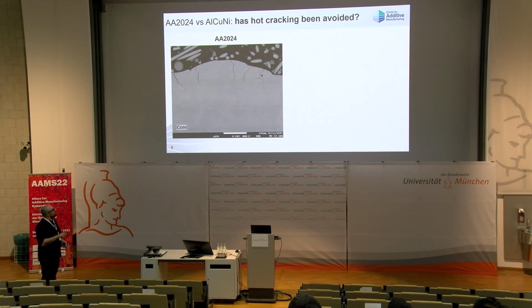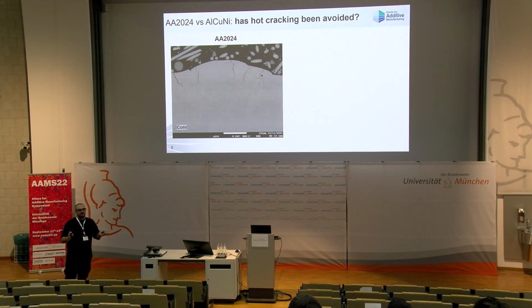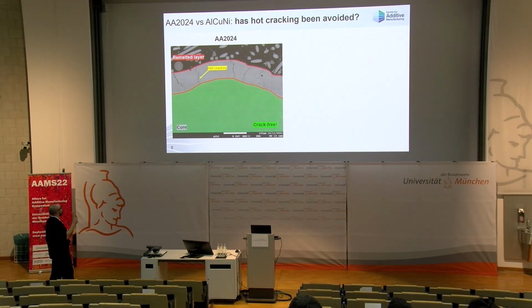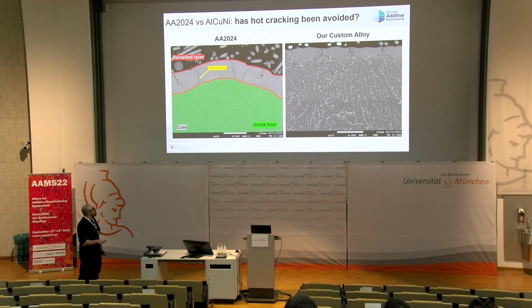And then remelt the top surface with standard parameters, which of course can produce hot cracks, as you can see here. What you can see is the presence of a remelted layer characterized by a lot of cracking and a crack-free microstructure in the core. When we do this with our custom alloy, of course the core is different. One is L-PBF material and the other one is melted material.